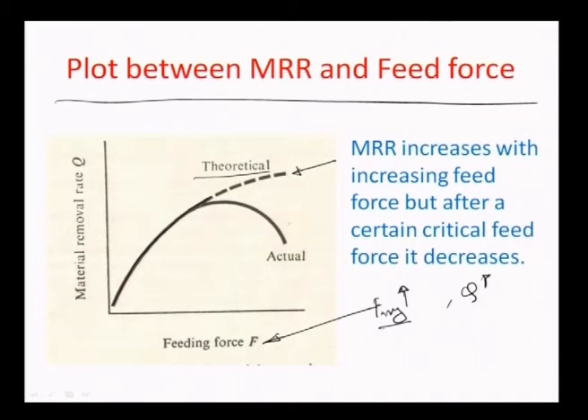But what is interesting here is that above a certain limit of the feed force, let us say above a certain limit of the F average force, there is a depreciation of the material removal rate, and the material removal rate comes down after a certain critical feed force. That happens because of a very important effect which practically almost always happens in these USM systems, which is also known as the grain crushing effect. Okay.